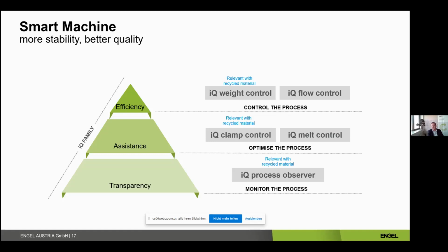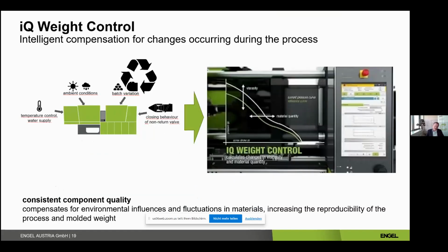Starting with the IQ weight control, what is the IQ weight control doing? The situation is, for example, and we showed this already 2 years ago at the last K show, we had a machine there with two hoppers, with two different suppliers of a material. It was a technical polymer, and these two different suppliers had two different melt flow indexes. And then we switched over from one hopper to the other, and the machine adjusted the parameters by itself in order to always have the same shot weight.